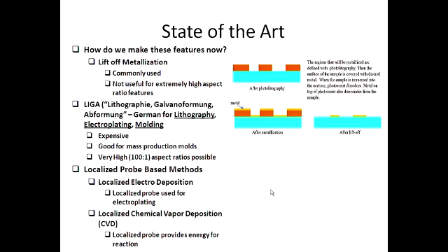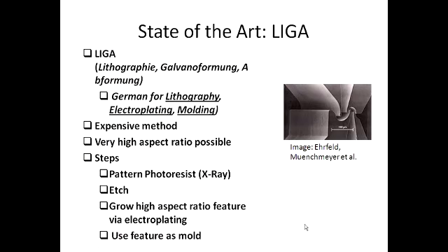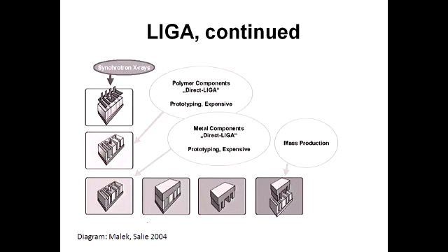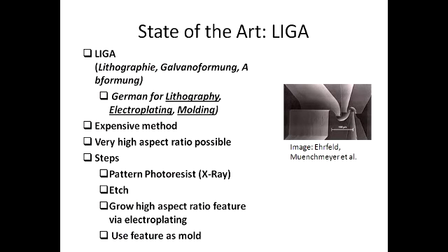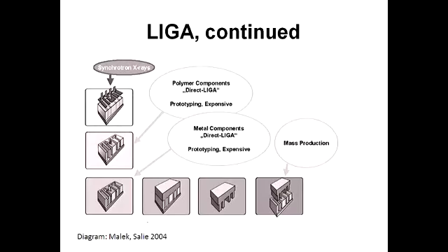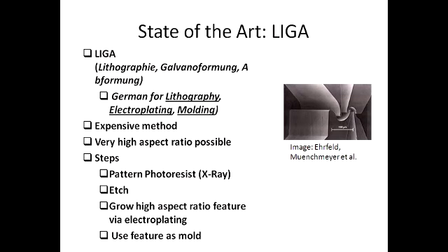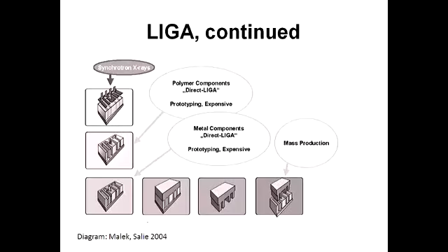Another method is LIGA. This method is a combination of lithography, electroplating, and molding. As you can see in this figure, at first we have an X-ray mask, and we expose that by X-ray. Then we use etching, and after that grow high aspect ratio features by electroplating, and at the end we have the features as mold. Because we use X-ray and also an X-ray mask in this method, both of them are very expensive, and that leads to an expensive method. This is very good when we need high aspect ratio features, but it's very expensive, and it's not possible for us to use this method for all of the applications that we need.